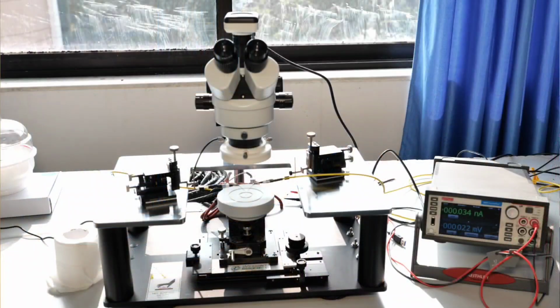But this material, gallium oxide, due to its very wide band gap, close to 4.9 electron volt compared to silicon which has 1.1 electron volt, gives us a very high breakdown voltage, which is the first and foremost requirement for any high power application device. At the same time its on resistance is also very low, which ensures these devices will have very low on-state losses, and they can also operate at reasonably high frequency.